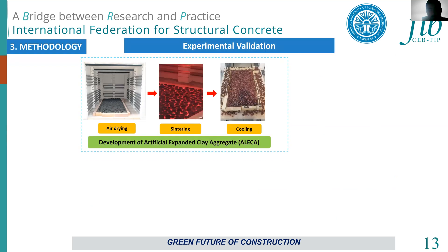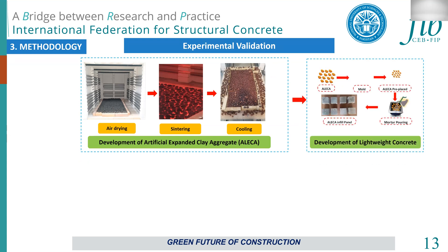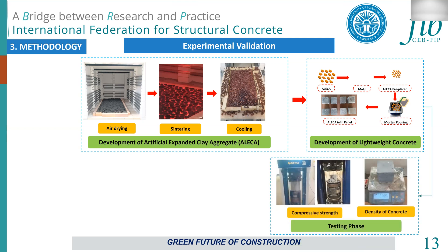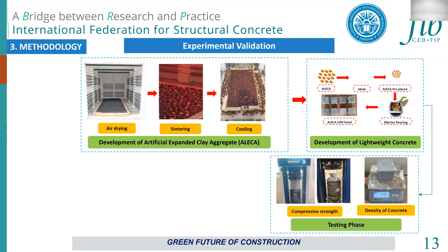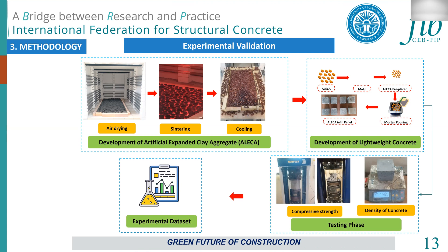For experimental validation, I selected artificial expanded clay aggregate. I collected different clay samples and, after initial geotechnical investigation, these clay samples were used to produce artificial expanded aggregate at different temperature zones. After developing the expanded clay aggregate, I utilized it to produce lightweight concrete based on expanded clay aggregate. Mechanical testing was conducted at different curing ages, with density and compressive strength as outputs.